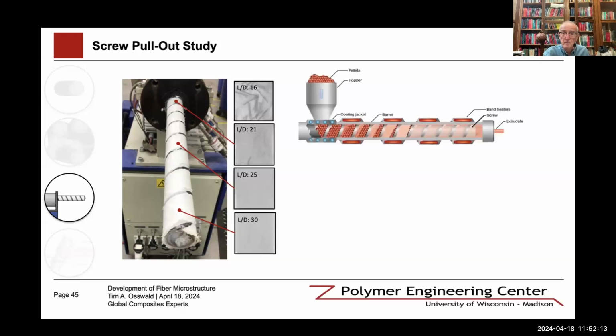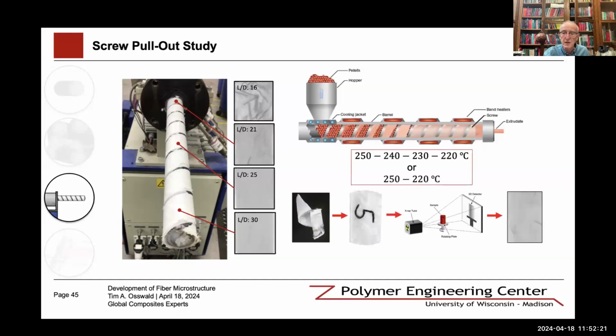This would be the conditions that we used and the different changes. In the pull-out experiments, we took out samples, we flattened out the samples, and then we did the micro CT analysis to get the images. Using the images, we found the coefficient of variance and the dispersion along the L over D of the plasticating unit.